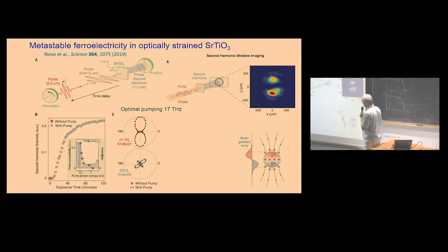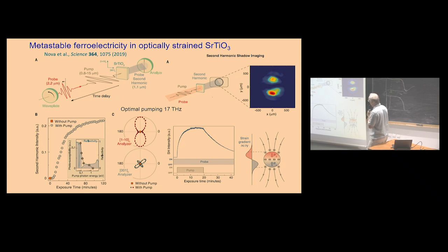In this case, the optimal pumping was 17 terahertz, which is again the highest frequency phonon in this strontium titanate. And they explain such creation of polarization by a strain gradient.